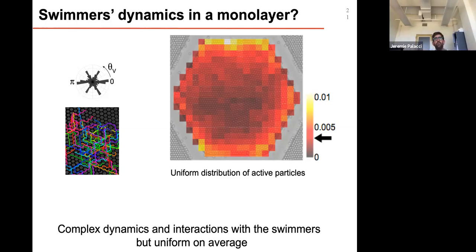And if you do so, you have this other thing happening: particles with persistent random walk, so basically active particles which move in straight lines and then make turns, tend to accumulate at boundaries. The reason is that they run, then they reach a wall, and then they slide along the wall. So if you confine active particles, after a transient, you will end up with all the active particles near the boundaries. Once again, you phase separated the activity from the rest of the passive monolayer, and therefore you cannot do the experiment. So what Sophie did in the experiment was a nifty experimental trick.